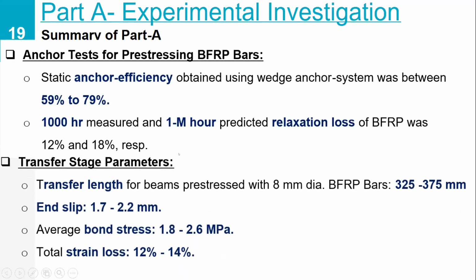The transfer stage parameters: the transfer length for these 8 millimeter diameter BFRP bars were between 325 to 375. The end slips were nominal. The average bond stresses that were obtained was 1.8 to 2.6 MPa for concrete having strength of 40 MPa. And the total strain loss was between 12% to 14%.